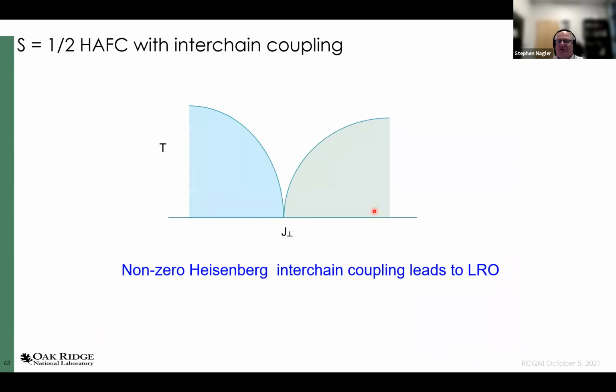But there's a bit of a complication, which is KCuF3 is actually a 3-dimensional material where it has very strong interactions along the chains, but weak interactions between the chains. And for this Heisenberg antiferromagnetic chain, any amount of coupling between the chains will lead to an ordered state. So I can make a little phase diagram that looks like this, right? Here's the coupling between the chains, here's the temperature. If I have absolutely no coupling, I do have this state that only supports spinons, which, by the way, some people would call a type of quantum spin liquid. But otherwise, I actually have some magnetically ordered state.